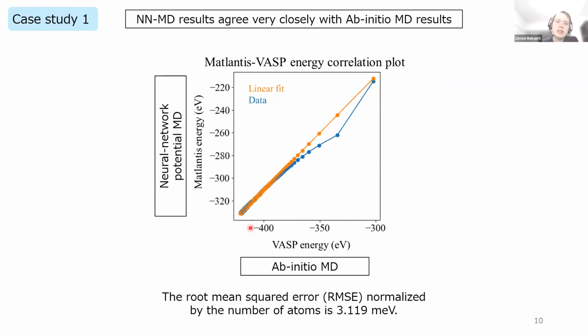And so in this case, we performed a downscaled size of the simulation because you cannot simulate thousands of atoms that easily in ab initio MD. And we plotted it versus the neural network potential MD from Matlantis, so the energy results. And as you can see, it performs really well. There's a slight deviation at higher energy, but that has to do with the input structure. And the mean square error is 3.12 milli-electron volts, which is a really reasonable number, especially when you compare it to other machine learning potentials nowadays too.